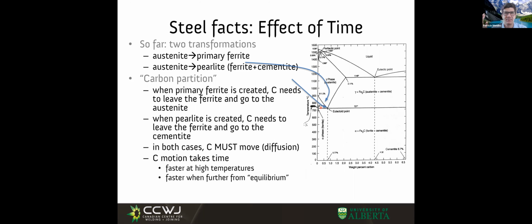What happens then? Well, what happens is that the carbon needs to get out of the ferrite. That is what is called carbon partition. And that takes time. How does it happen? Typically, the limiting factor is the diffusion for the carbon to get out, right? We talked about diffusion bonding, this thing in which the carbon atoms are moving through the crystalline lattice. In this case, it has nothing to do with bonding, but everything to do with atoms migrating through the lattice.